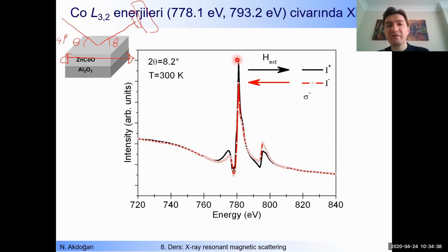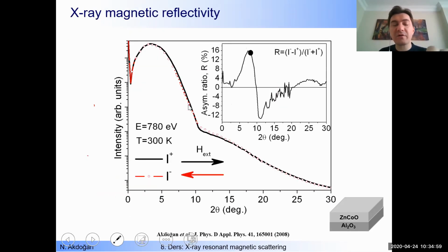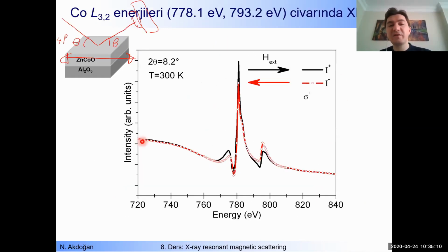There is also difference. This is the maximum of the black one. This is the maximum of the red one. So we have also features around those L2, L3 energies. So it means that you have magnetic signal, but as we have done for X-ray magnetic reflectivity, if we plot a asymmetry ratio, we can see the difference between two curves here. The difference between two curves can be seen better if we plot a asymmetry ratio.